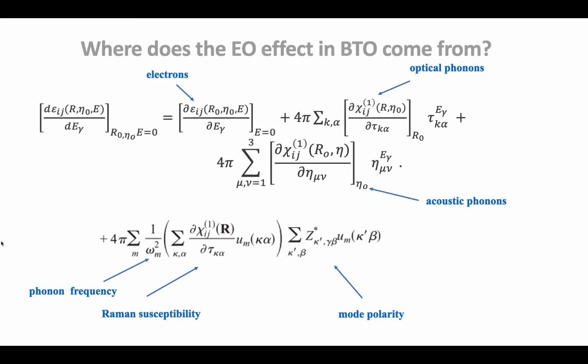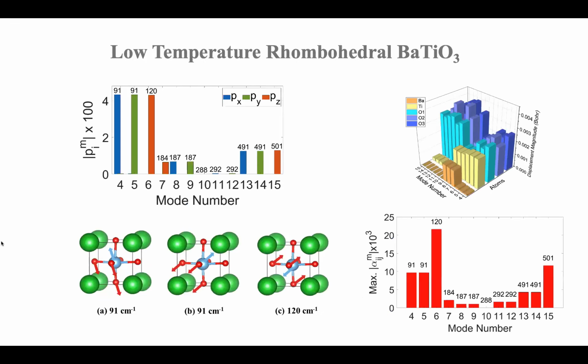So this is the formula I already showed you. If you look at the ionic phonon response, it sort of looks like that. So this is the derivative of chi1 with respect to atomic displacement. So that's the Raman effect. This is the Born effective charge. This is the frequency of the mode. And so if you want to do first principle calculations, your best bet is rhombohedral phase because it's dynamically stable. And here, everything you can actually understand, everything works. First principle theory works perfectly for what you're not interested in.